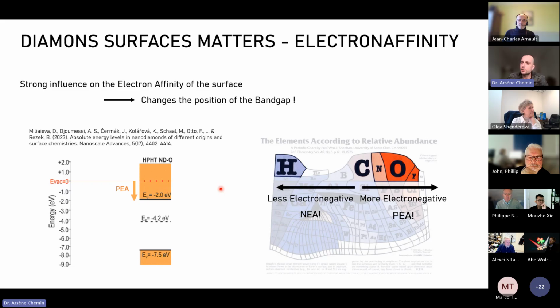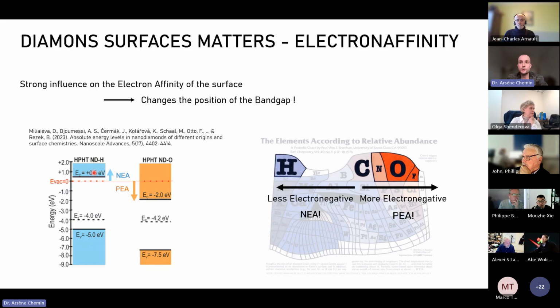On the other end, you have the hydrogen on the left side of carbon. Because it's on the left side, it's less electronegative, meaning that it will lead to a negative electron affinity. And if you check the measurements, you find out that indeed the hydrogen terminated nanodiamonds have a conduction band lying above the vacuum level. And that is very interesting, because what does it mean? It means that every time you excite electrons to the conduction band of the diamond, those electrons will tend to simply escape from the diamond. And this property is quite unique. I don't have in mind any other material that has a conduction band lying above the vacuum level. So diamond can emit electrons in vacuum. That is already known since a long time. But as we will see, they can also emit electrons in a liquid environment. And that is very handy, because those electrons in the liquid environment are very reductive and can be used for electrocatalysis.